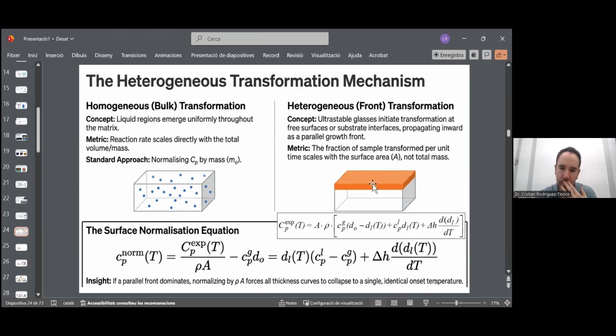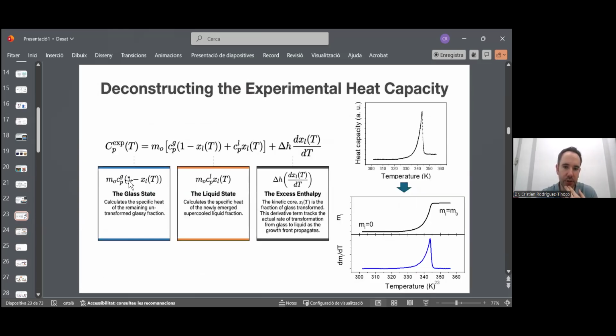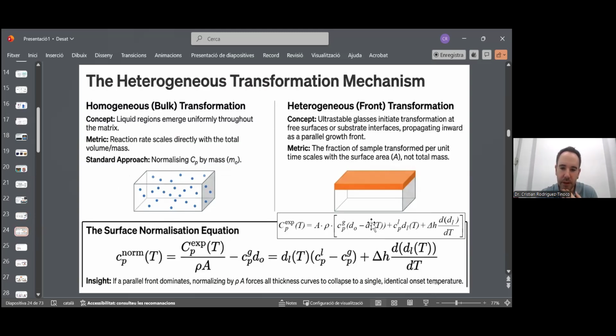We can do this by assuming that the transformation takes place via this front that starts from the surface and propagates into the bulk. Basically, we change the transformed fraction we had in this original expression. The x is the transformed fraction. We can change this transformed fraction with this d, which is the thickness of the part that has been transformed into the liquid. The liquid thickness, let's say, depends on temperature, and time of course, but temperature here because the temperature depends on the time.